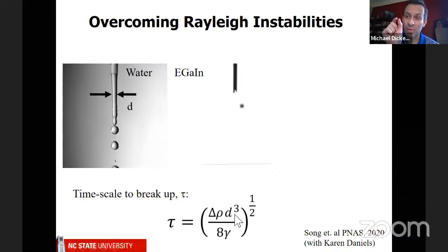So what this means is if you make something really small, it's going to break up really fast. Another thing that matters is the surface tension. So the bigger the surface tension, which is squeezing like this, the faster it's going to break up. In other words, the shorter the time scale. And so with liquid metal, because we're going to make a really small stream, actually about 100 microns, that's about the size of a human hair. And remember, it's got this enormous surface tension.